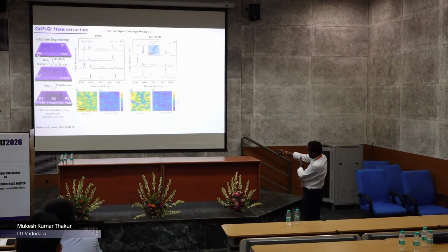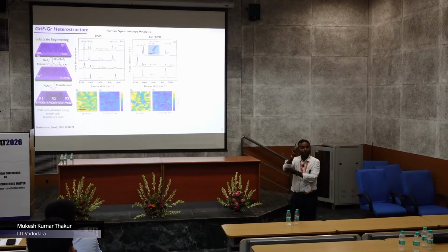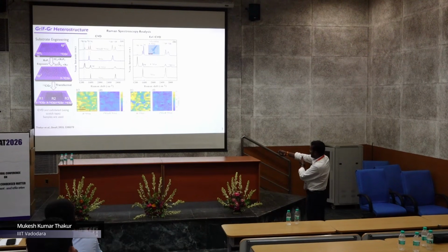So this is our pristine monolayer graphene with the carbon 12 isotope. You can see there is no D mode. Okay, then we expose it to fluorination. Now very nicely this D mode came. The D mode is also an indicator of sp3 hybridization. And then you also have the D prime, G, and the 2D. So it's basically now defective graphene. We created the defect in this one.